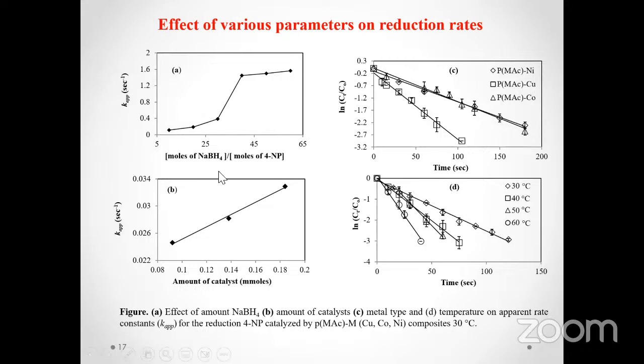So this is how we first investigated the concentration of the reducing agent, and we found that when the concentration of the reducing agent was increased to 50 times, it had no effect on the rate of the catalytic reaction. So all the reactions were carried out using a concentration of reducing agent 50 times higher as compared to the reactant. The effect of change in concentration of the reducing agent was not considered, and pseudo first order kinetics was applied, and it was observed that in case of all the composites containing nickel, copper, and cobalt nanoparticles, we obtained significant catalytic activity.